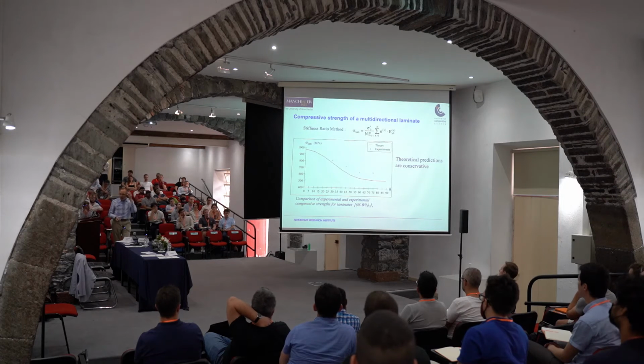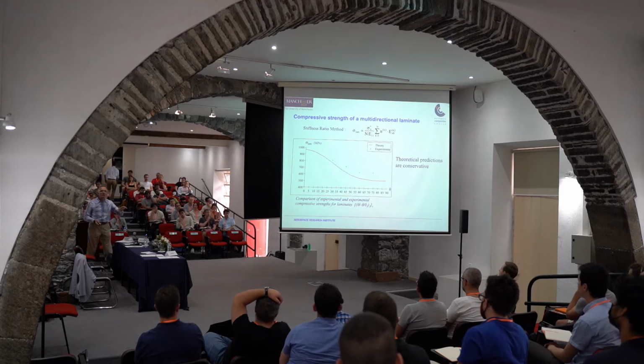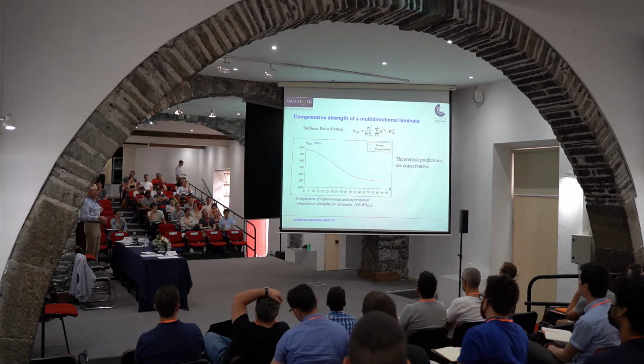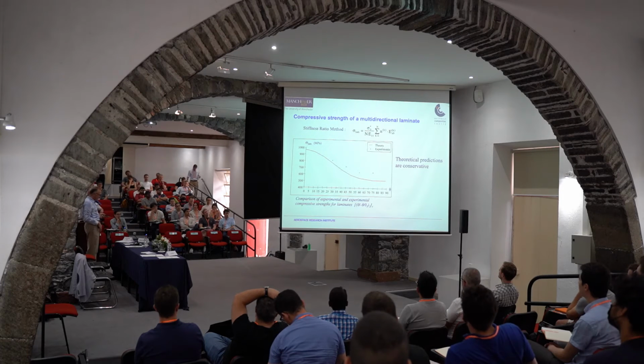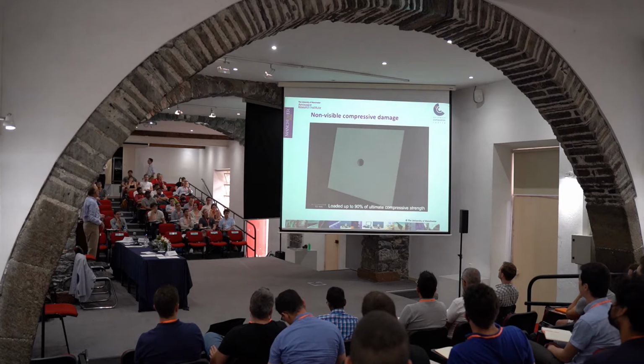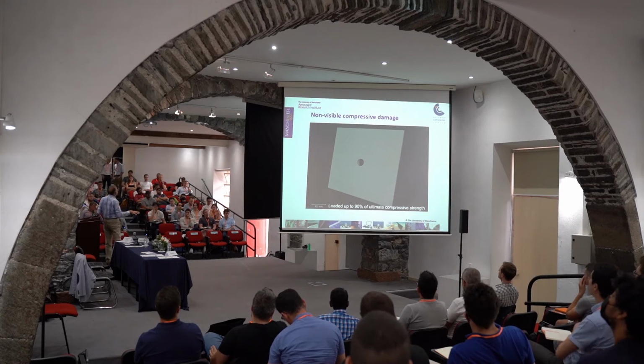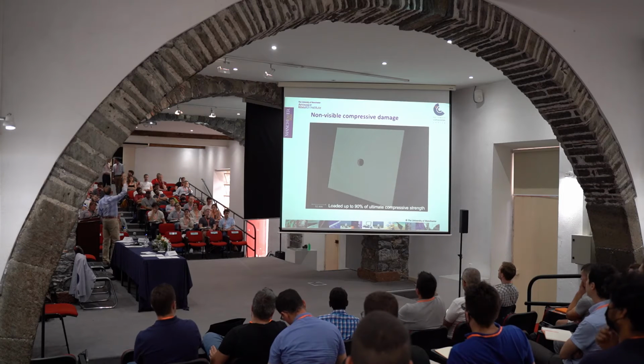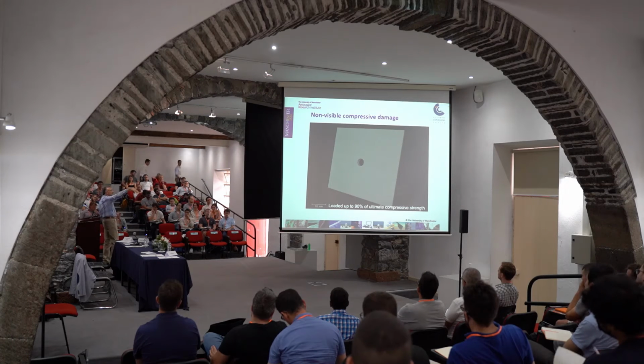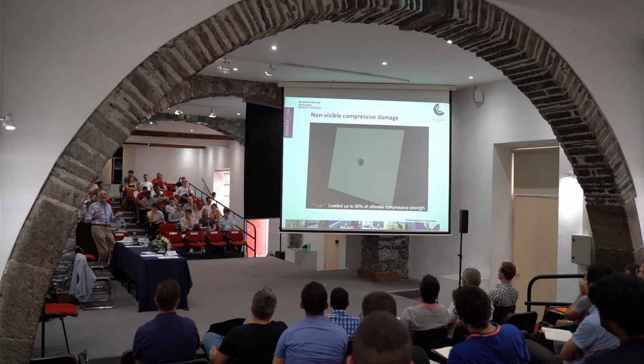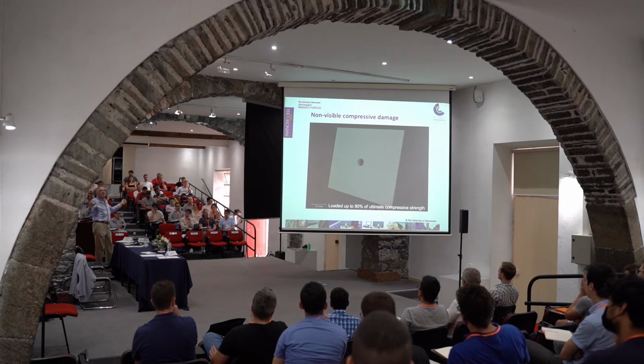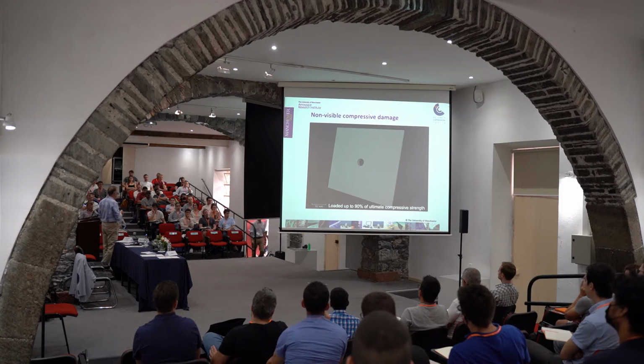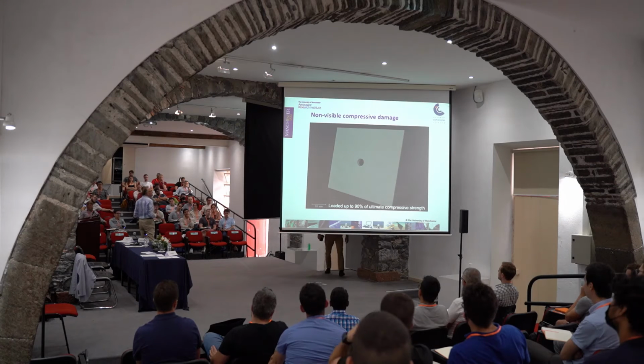And then, of course, once you have the critical stress at which the zero ply will buckle, you can calculate the compressive strength of any bidirectional laminate ±theta. And all this damage that we're talking about is non-visible damage. Here is a 0/±45 symmetric laminate, 3 millimeters thick, which is loaded in compression and has been loaded at 80% of its ultimate compressive strength. And there is no damage, or at least non-visible damage. I mean, someone is going to say, yeah, I can see little damage there, but maybe that's due to the drilling process.